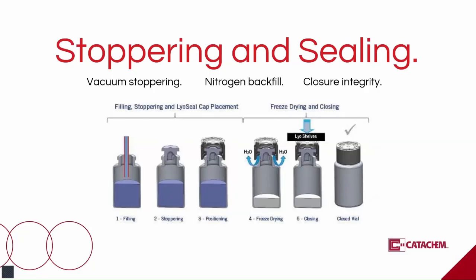At this point, you have choices. Stopper under vacuum, backfill with nitrogen or other inert gas, or do both. Maintain vacuum during stoppering and then apply an inert gas backfill strategy, depending on the product needs and the equipment configuration. The decision should be driven by oxygen sensitivity and closure integrity considerations.